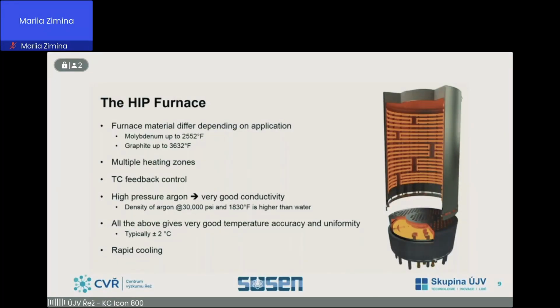The HIP furnace can be made for several different materials and temperature ranges, for temperatures up to 2000 degrees Celsius and pressures up to 2000 bar. The density of argon at this high pressure and high temperature is very close to water. The densification process is a combination of plastic deformation, creep, and diffusion. Isostatic pressure means that the same pressure is acting on all component surfaces in all directions, and it is achieved by a gas pressure medium.